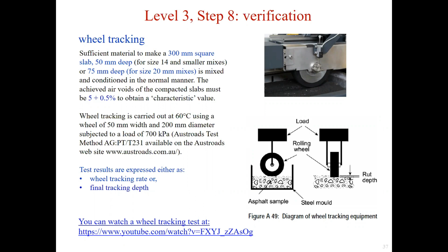The test is normally carried out at 60 degrees using a wheel of 50 millimeter width and 200 millimeter diameter, with top load generating pressure of 700 kPa. The results are expressed in terms of wheel tracking rate or final tracking depth. You can watch a wheel tracking test demonstration through the link below.